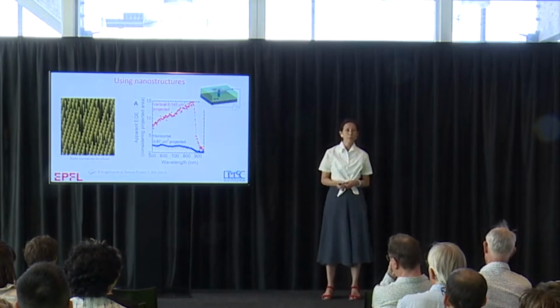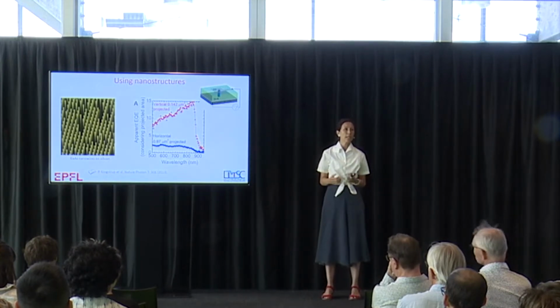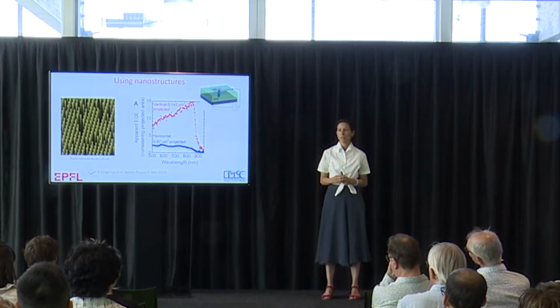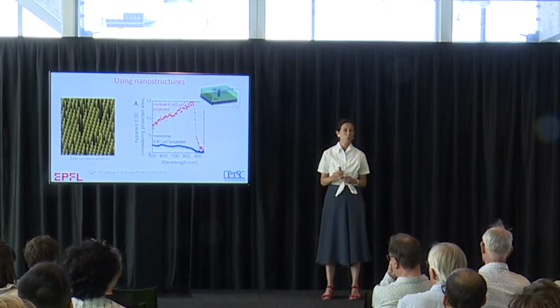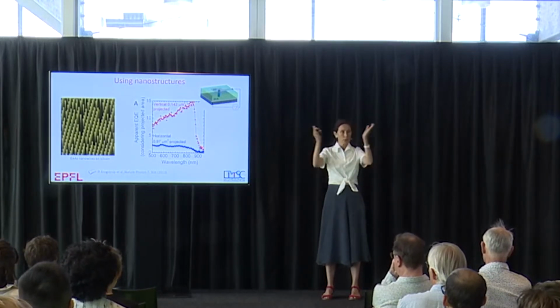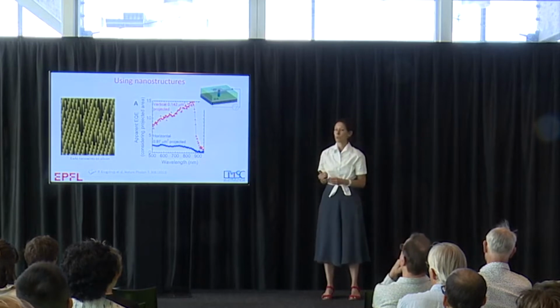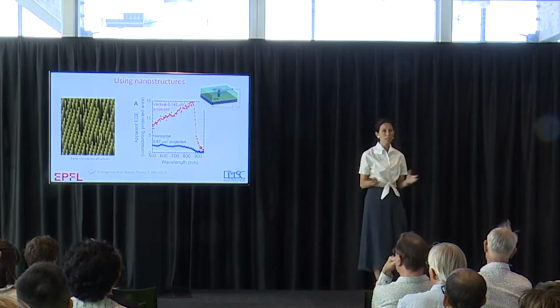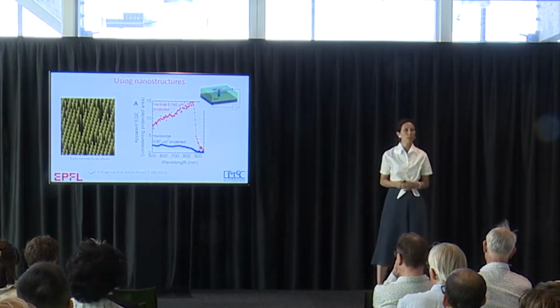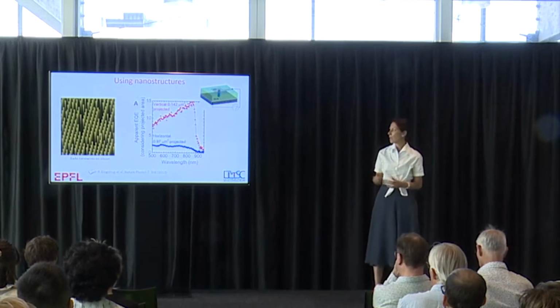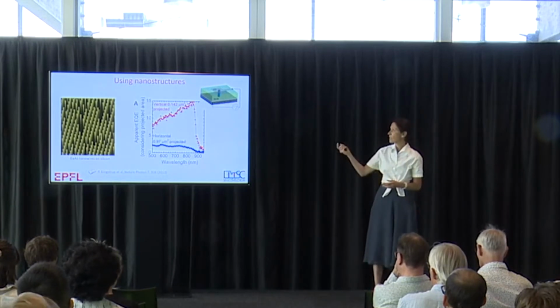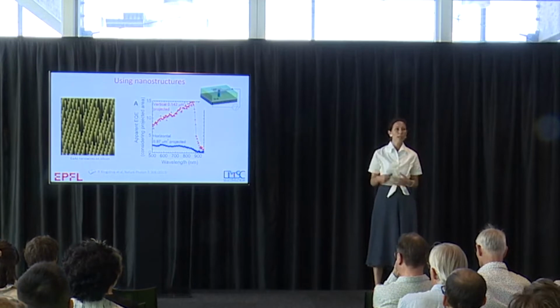You also see that per nominal photon you have 15 electron hole pairs. And this is not that every photon creates 15 electron hole pairs, it is that in fact you're absorbing 15 photons because you collect these photons around. And so this was the first demonstration that this effect that we see, that the wires really collect all these photons around them. If you design them well, then it can be useful for photovoltaics. And this has kept us many years trying to get high efficiency devices.